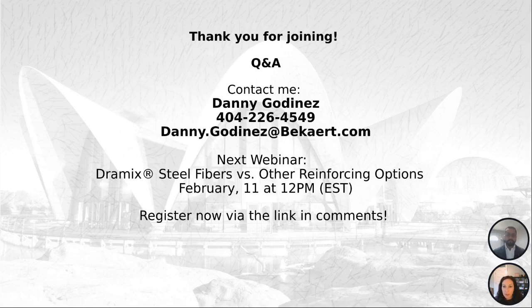The next question, Danny, is: for pouring in a checkerboard pattern, what would be the recommendation for the time between adjacent pours? Very good question. We've seen that for low shrinkage mixes, contractors have been able to come back within 12 to 24 hours, depending on how big the panel is and how big the project is. It is pretty reasonable to expect a 24-hour period. But if your construction is a small project and doesn't allow for more than 12 hours, 12 hours oftentimes would allow for that initial shrinkage to take place. The longer you wait, the better to minimize the opening between panels, but I would say the minimum would be 12 hours between panels.